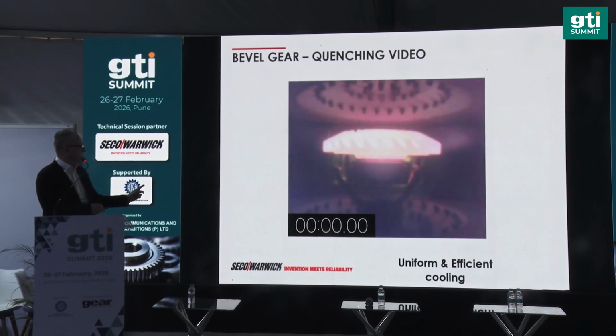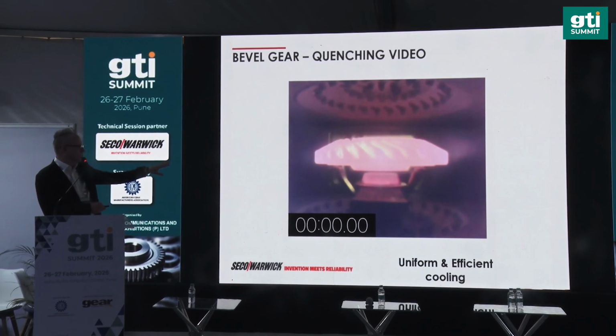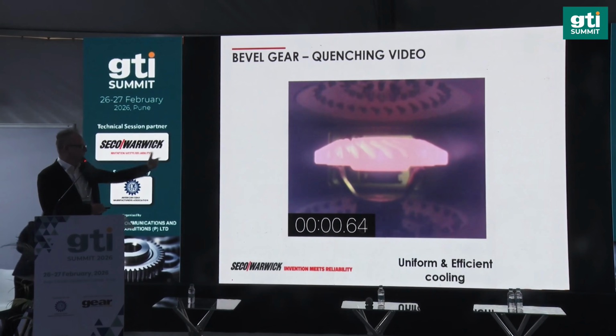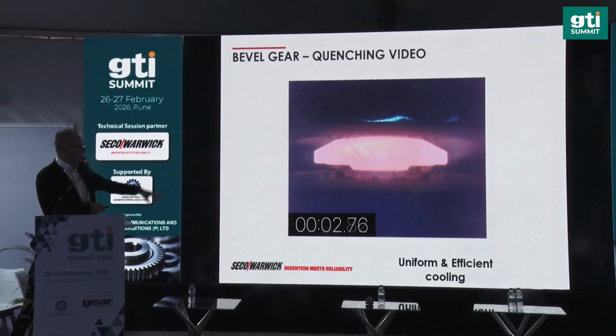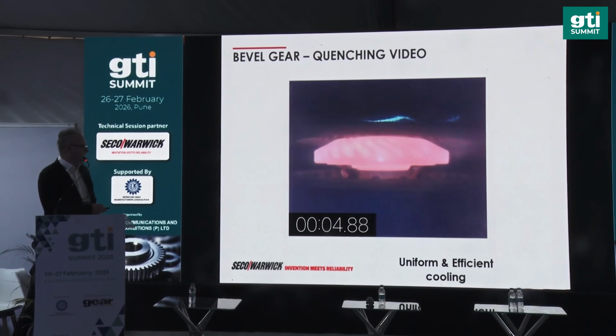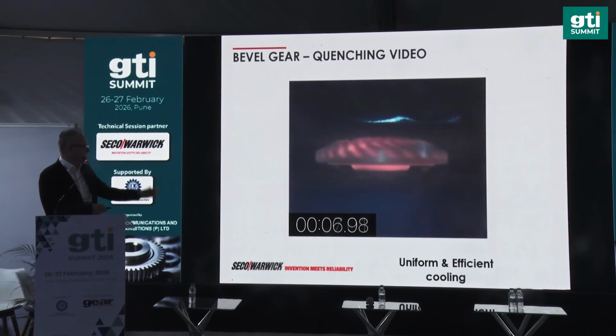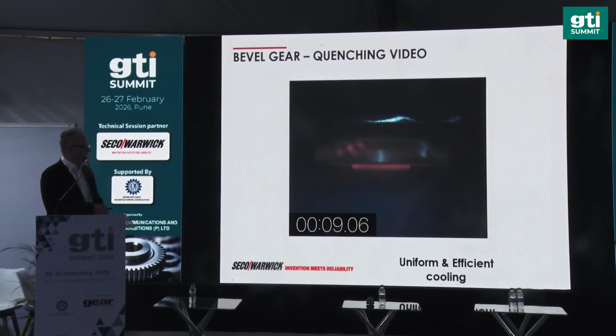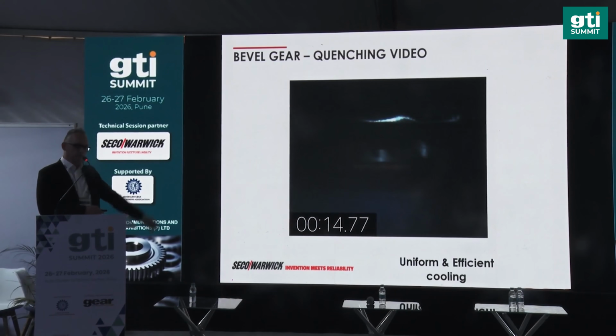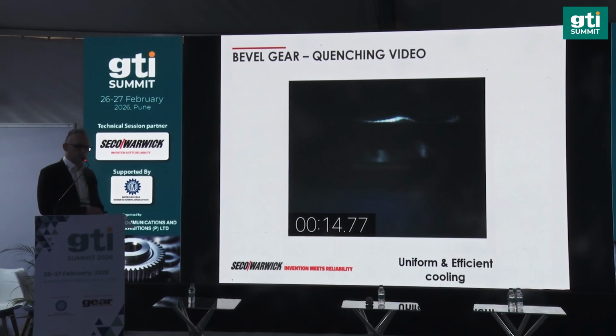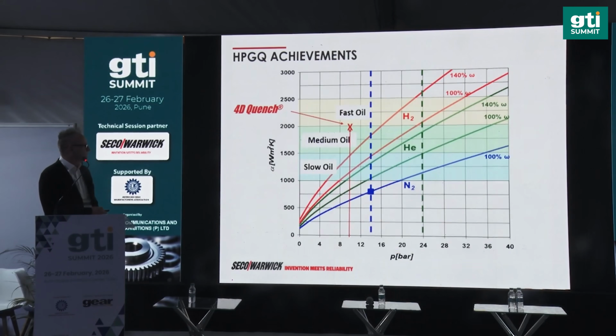This is an example of such a system where one part is coming into the quenching chamber. Prior it was carburized, and then the quenching process starts. So as you can see, in addition to flow of the gas from top and bottom, we rotate the parts in order to make the process even more uniform. And within several seconds, the part is ready to be proceeded further on.